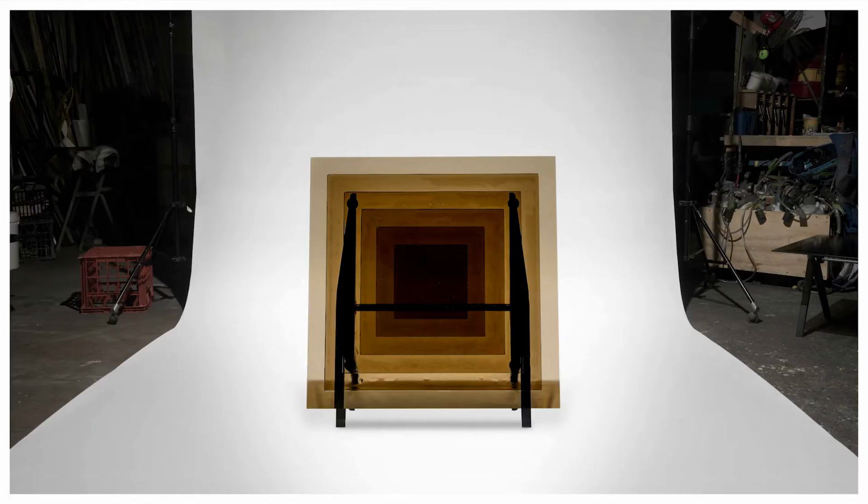So we're one of the only companies left in Australia with a kiln that's about 2 by 4 meters in size, and we fire glass in the kiln bed. Adam really pushed the limits with this one because we were stacking 6 layers of glass together, and it was all kiln fired over a 2-day process where each layer of glass was melted together to form one new piece of glass. We did a lot of tests, as you might have seen in the early photos, and wrong temperatures caused the glass to explode and shatter, including a full-size piece. So it was getting a little bit stressful at the end. But after lots of testing and lots of prototyping, we got there.